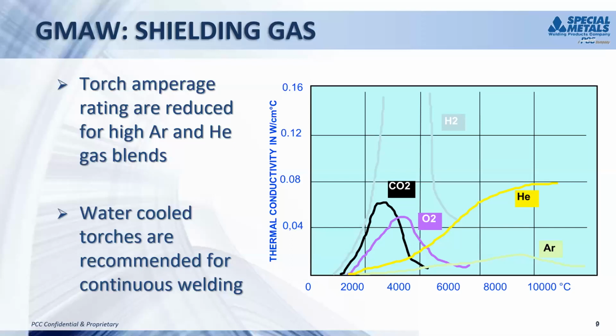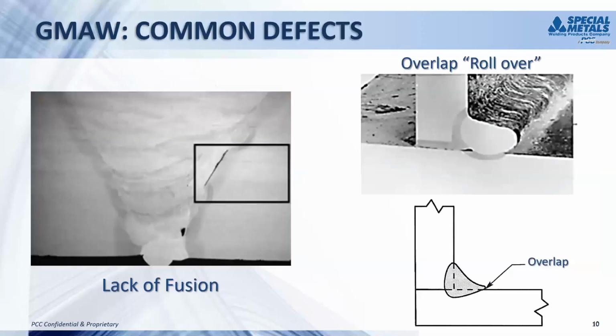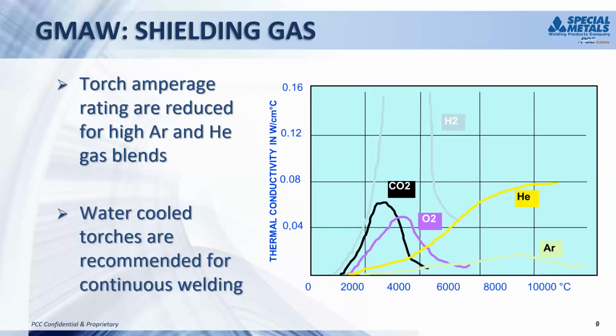The other thing we recommend on these is the water-cooled torches. Again, with the higher resistivity of nickel, you build up a lot more heat, and when you're continuously welding, those contact tips just don't get the cooling they normally would get with the CO2 shielding gas. So if possible, and there is continuous welding at higher amperages, a water-cooled torch can really save you a lot of headaches and burn backs and stops as you're trying to weld.